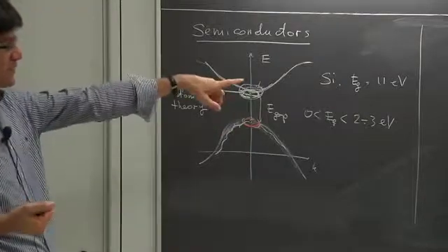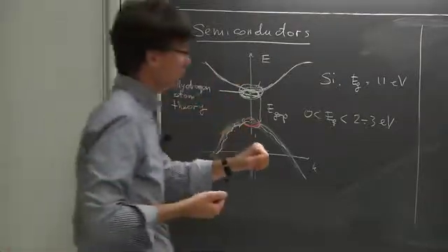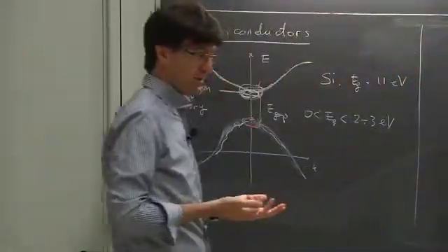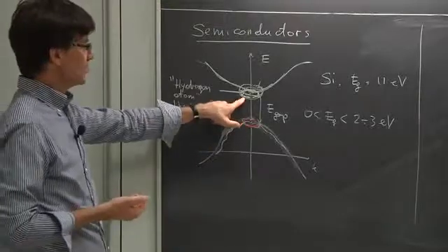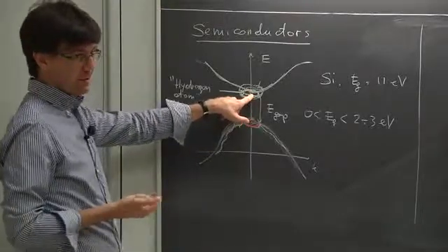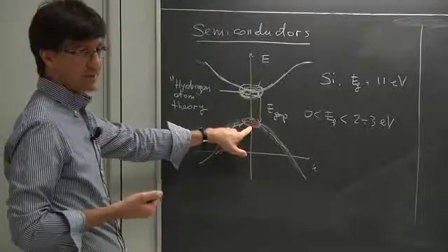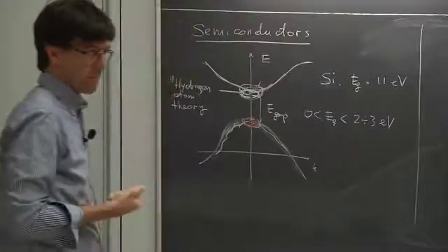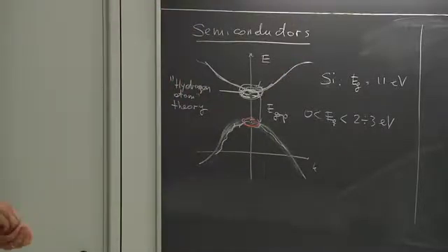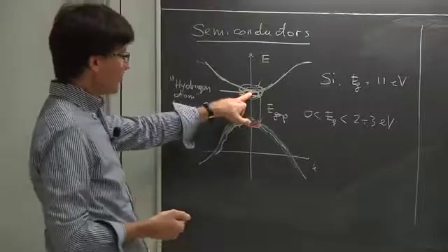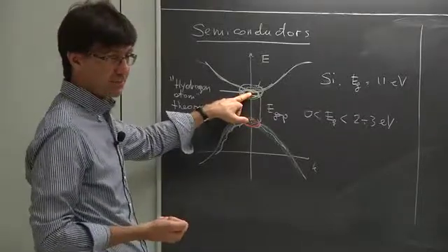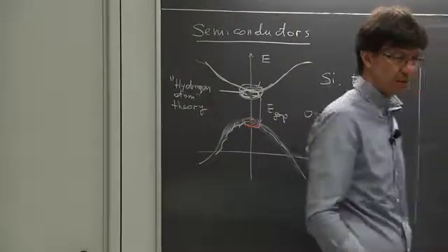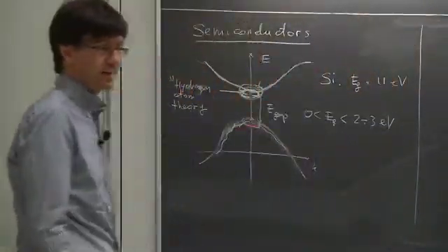As soon as I introduced the possibility of doping my system, that is, of introducing aluminum or phosphorus or some other impurities, I'm introducing the possibility to add electrons or to remove electrons just by playing with the number of impurities that I add to my system. So I can construct a silicon crystal where there is a large number of electron carriers here. If you want to do that, I simply have to throw a large number of phosphorus atoms in when I grow my silicon crystal.